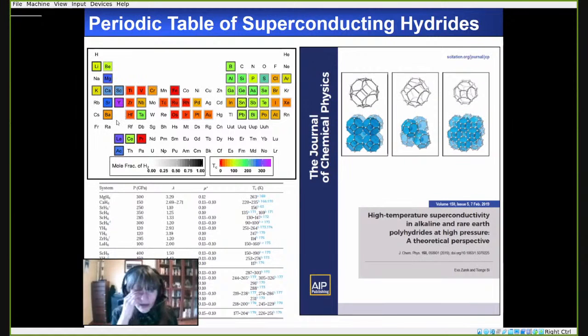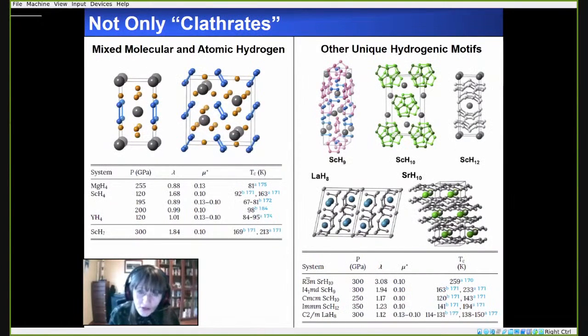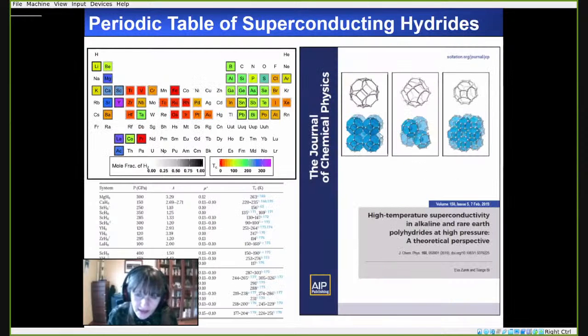And what we find for the binary hydrides that have the highest Tc values, such as yttrium and lanthanum hydrides, is that the hydrogenic lattices assume these very interesting clathrate-like cage structures, and the metal atom is situated within the clathrate. So they have these three-dimensional hydrogenic lattices, which is very unusual, taking into account what we know of the bonding of hydrogen at 1 atmosphere. There are other hydrogenic motifs that have been observed as well. For example, atomic hydrogenic lattices or other unique motifs such as one-dimensional or two-dimensional sheets and fused five-membered rings. However, these typically have lower estimated Tc values than the clathrate cages.